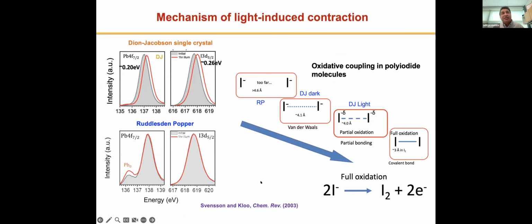So we wanted to really understand what was causing this light-induced contraction. And so we performed X-ray photoelectron spectroscopy. Again, this was an in-situ measurement performed here at Rice University, where you would put light on the sample, look at the XPS patterns, and then do the same experiment again and look at what was really happening to the bonding sites for the Pb 4f and the iodine 3d orbitals.